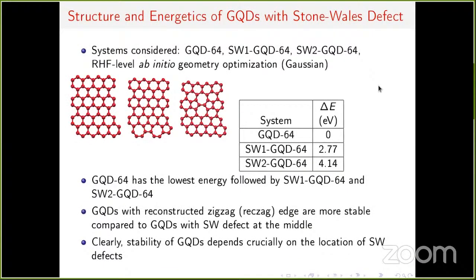So we considered three different types of quantum dots. On the left-hand side, we have a rectangular quantum dot with 64 carbon atoms called GQD64, which is pristine without any defects. In the middle, we have the same quantum dot, but with a Stone-Wales defect at the edge. Here you can see heptagon and pentagon shapes at one of the edges. We call this SW1. The third one is again a 64-atom quantum dot with a Stone-Wales defect. You can see pentagon, heptagon, pentagon here, a Stone-Wales defect right in the middle of the quantum dot.